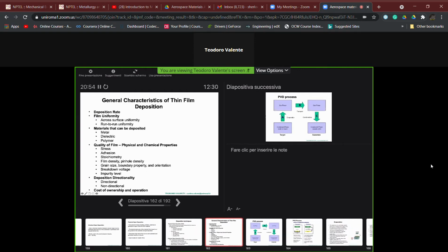For the general characteristics of thin film deposition, as we will see also later, we do have very low deposition rates in an optimized process. I have in mind, let me say, what is going to be used, for example, in a standard way for wear resistance coatings in order to achieve, for example, 5 microns of coating thickness. We could need a processing time of the order of 5 to 10 hours. So that means that the deposition rate is very low if compared with the thermal spraying processes. Then we do have the parameters which must be controlled, which refer to the film uniformity, both across surface uniformity and run-to-run uniformity.